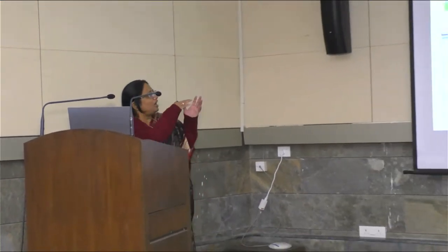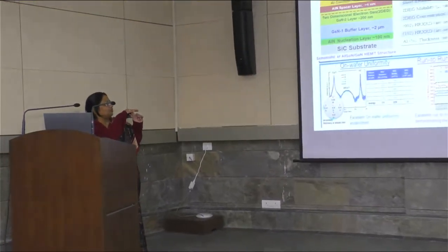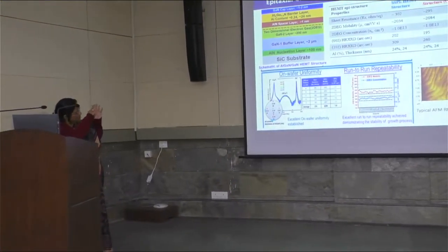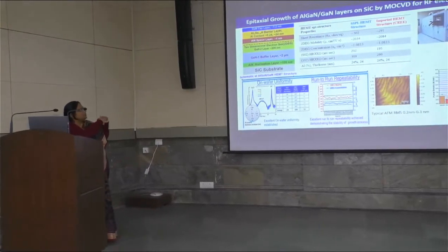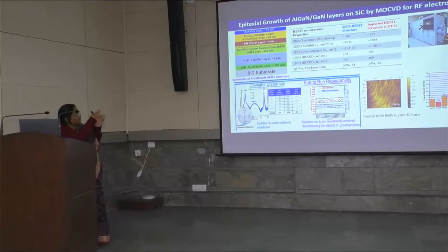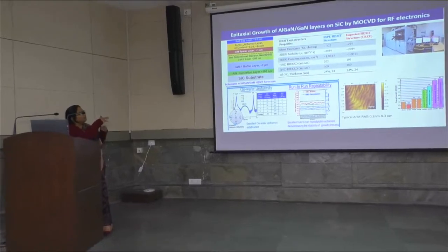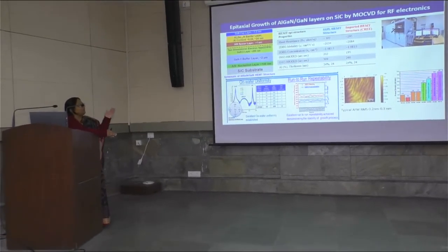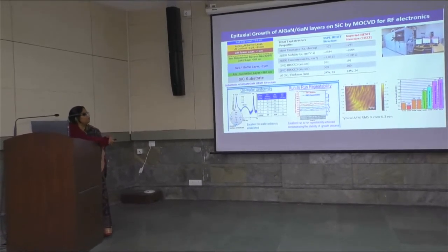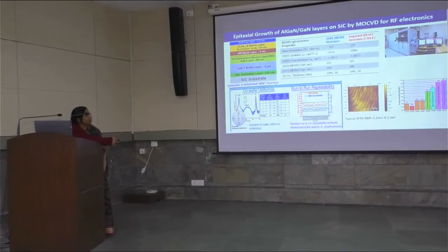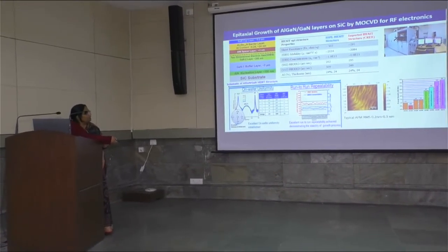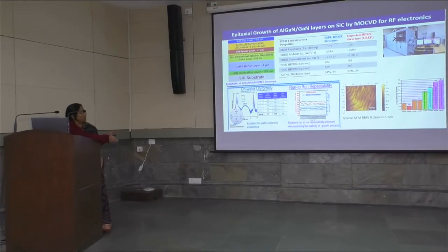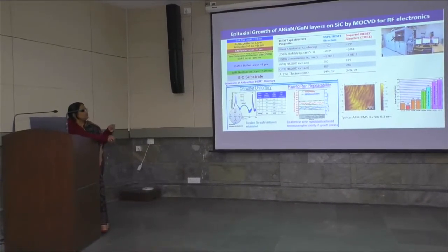And the challenge here is that each of these layers has to be grown at a different temperature. And you have to have very atomically sharp interfaces also. So these are the challenges. This material growth process has to be optimized. And then we have developed the device-grade material. It is not as trivial as it sounds because it takes a lot of iterations and characterization before we reach there. And so then we can look at the on-wafer uniformity and run-to-run repeatability. And typically this is the AFM measuring the surface roughness, which is as good as state-of-the-art material available.